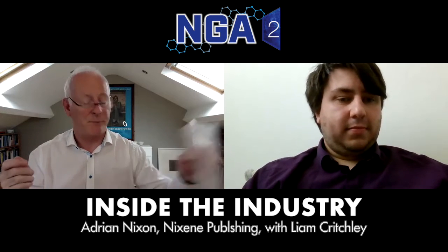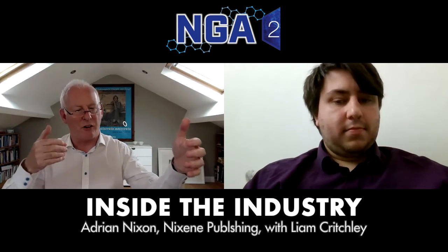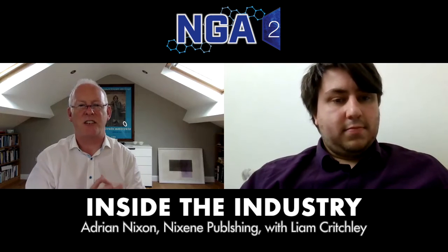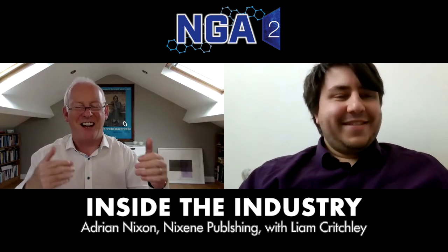Liam, I think you and I both know that there's something called a roll-to-roll production method of making graphene on copper foil. And it needs to be made fast. We can't just use the current lab methods of making graphene, because I ran a calculation a while ago and for the amount of graphene we're going to need, it would take somewhere in the region of about 10,000 years to make enough at current speeds.